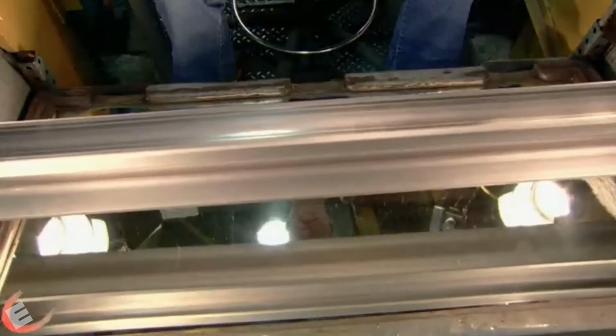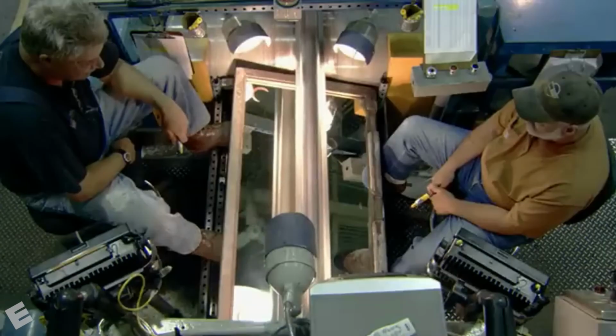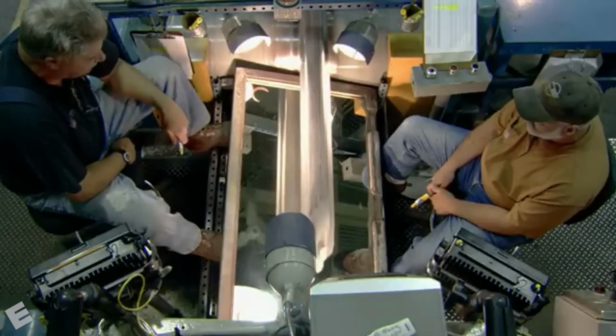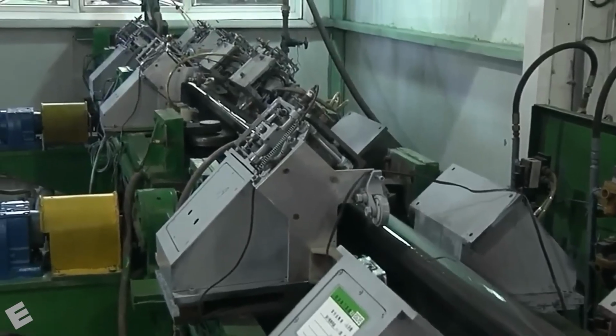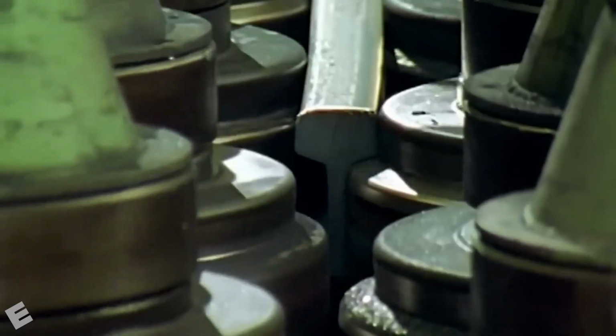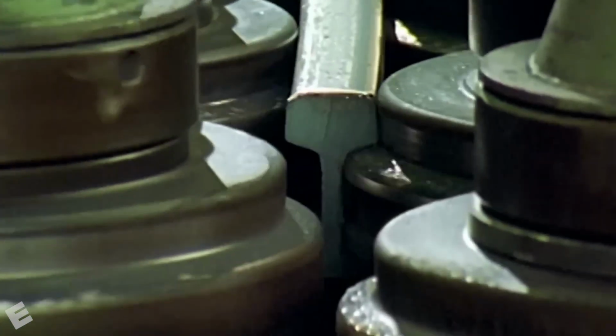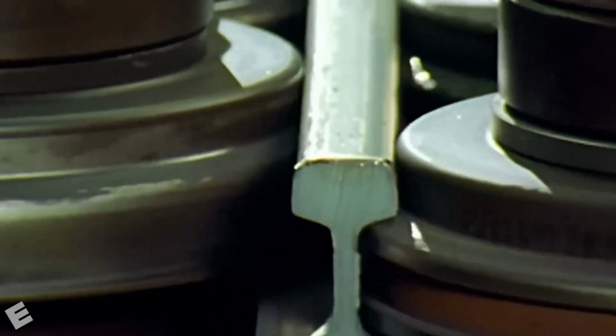Additional systems search for defects that cannot be seen from outside. Magnetic testing can reveal certain cracks or surface irregularities by measuring disturbances in a magnetic field. Ultrasonic probes send high-frequency sound waves through the steel. Reflections from those waves can reveal internal inclusions, voids, or cracks hidden beneath the surface. If the equipment detects a suspicious signal, the rail is examined again. Any defect that exceeds the permitted standard can cause it to be rejected.